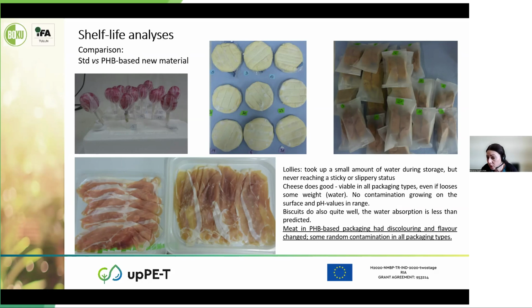Biscuits also did quite well. Indeed, the water absorption was less than predicted. As you can imagine, the meat performed in a different way because the challenges related to this fresh product are different from the others. Indeed, it had discoloring and flavor changed very quickly, and some random contamination was there.